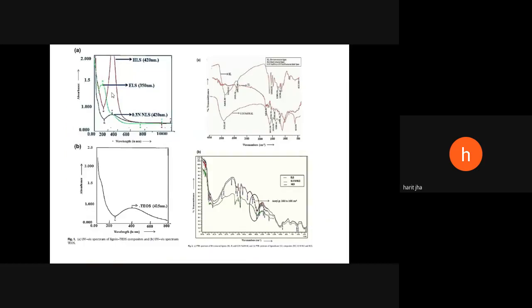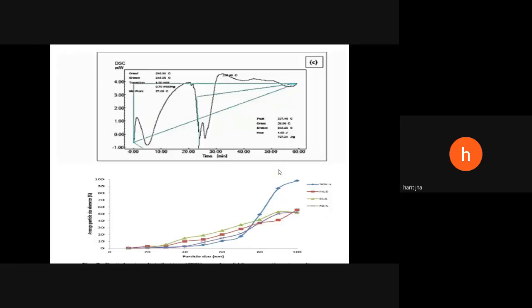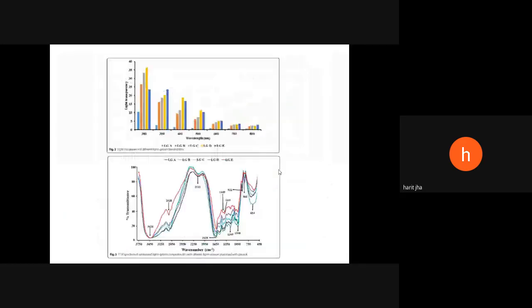This is a UV visible spectrum of the lignin-TEOS composites, FTIR of lignin-TEOS composites, DSC and particle size distribution, then FTIR.